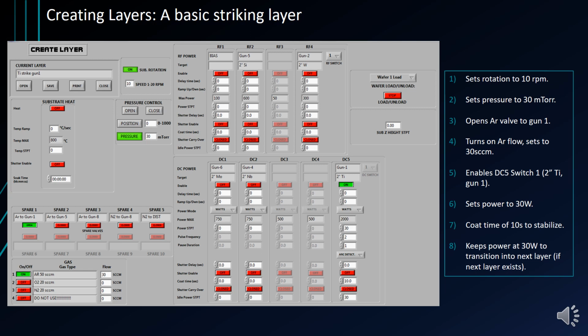No shutter delay is needed here because we aren't yet ready to actually coat anything. This is just to ignite the plasma. I don't enable the shutter because we don't want to open it. I've set the coat time to 10 seconds simply to give the plasma some time to ignite and stabilize. Shutter carryover is closed since we never opened the shutter in the first place. And lastly, the idle power is set to 30 simply to keep it at the power that we set it at. So what this recipe does is exactly like what we just did manually.